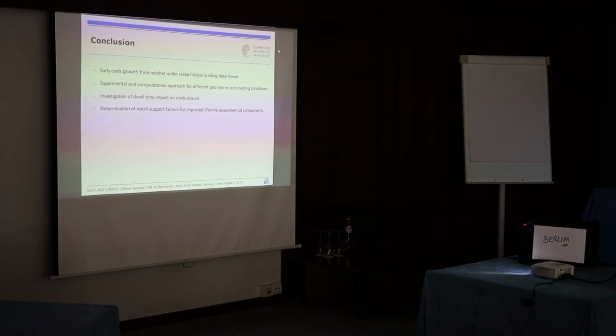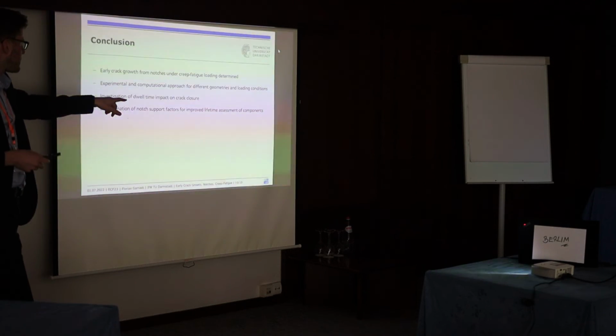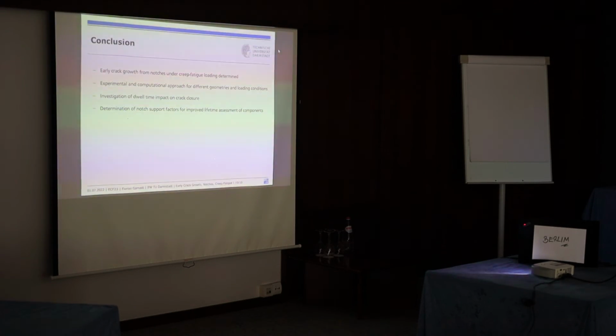Let me conclude. I showed you how we compute early crack growth from notches under creep/fatigue loading. I showed that we use different geometries, different loading conditions, and different materials. And I pointed out one major finding here, which is the impact of dwell times on crack closure.